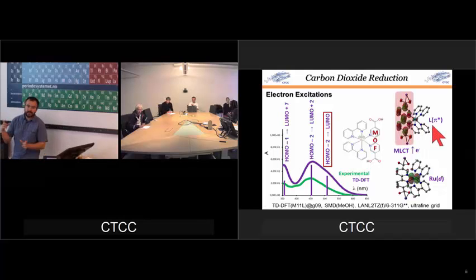It is on the ligand that has the carboxylates, and therefore is the ligand defining the direction along which the MOF is growing, so that by doing these electron excitations, we are injecting electrons into the MOF itself, which is the target, of course. And so now we can start from here. You can speculate modifications, for instance, introducing electron withdrawing groups within these rings that will lower this energy level even more, so that this will be even more red shifted.